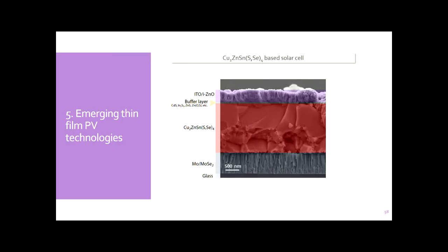This is the typical structure of a CZTS solar cell, and it's the same as CIGS. Why? Because during 10 years we were trying to modify this structure and adapt it to the kesterite, and during 10 years we failed. We are with the same structure as at the very beginning. Right now we really found that the problem for the moment is not the structure, it's the material itself.